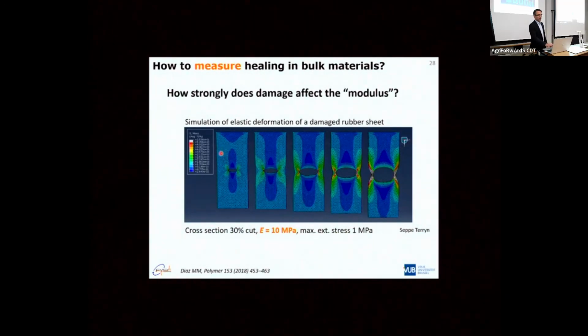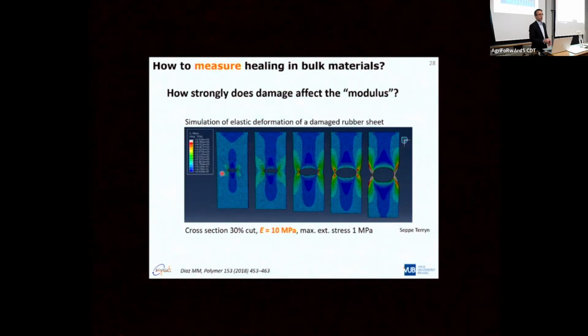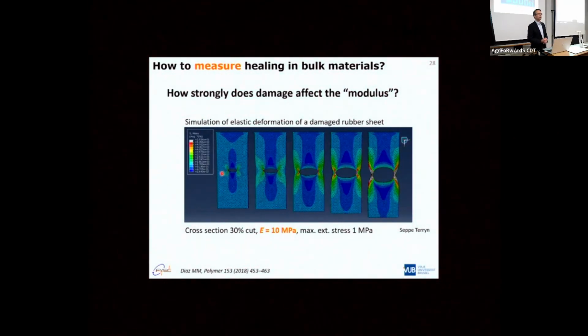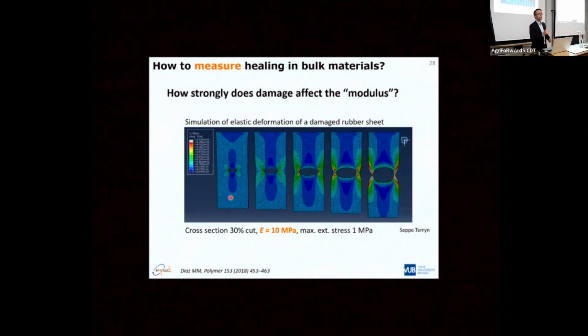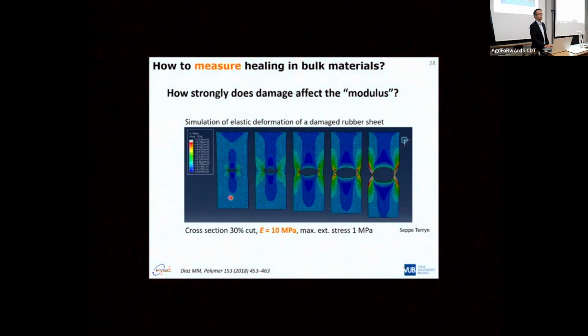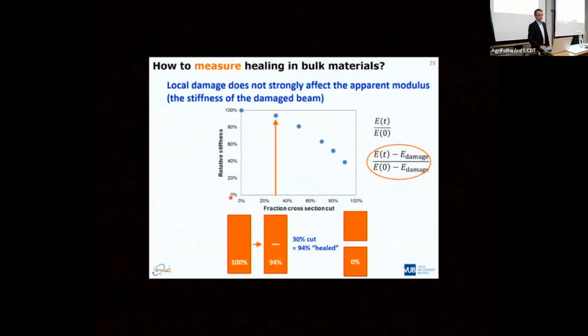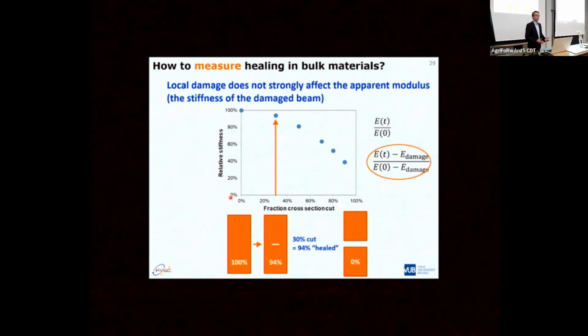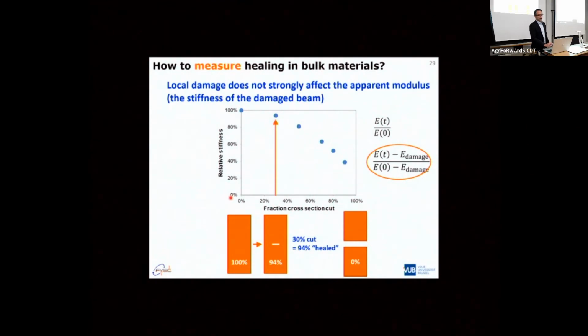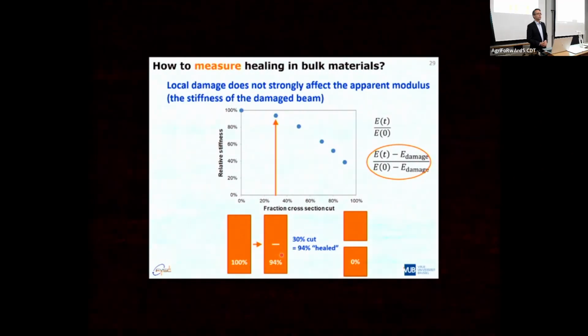Well, if you take a bar, you cut it for 30% in the middle, and then you apply a loading on it, a tensile loading. Of course, only there you will have a smaller cross-section, so only there you will have larger extensions. And the rest of your material will be loaded and straining in the same way as when it was not damaged. So that means that the apparent modulus, maybe I should say the stiffness, of the damaged beam for a 30% cut is still 94% of its original value.